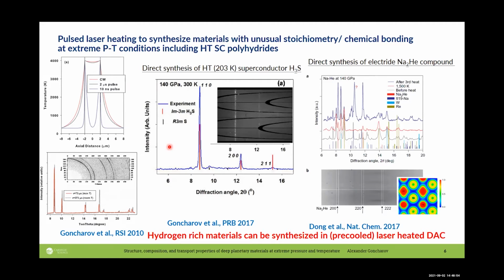Our development was that we quickly realized that, for example, with nanosecond pulses you can reach very high temperatures beyond 10,000 degrees. But unfortunately, when you look at the temperature distribution in finite element calculations, you see that you don't really heat the bulk of the sample, you just heat the surface of the sample. So we realized that it's important to do microsecond pulse heating, because this is more comparable to the propagation of the thermal waves.